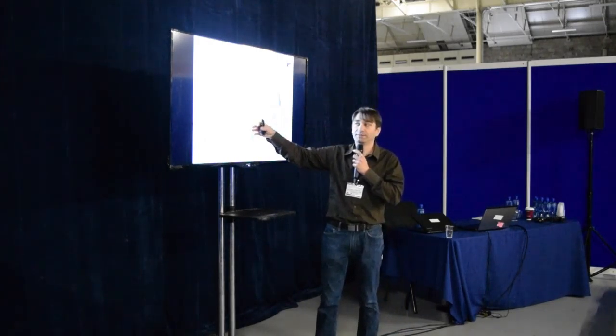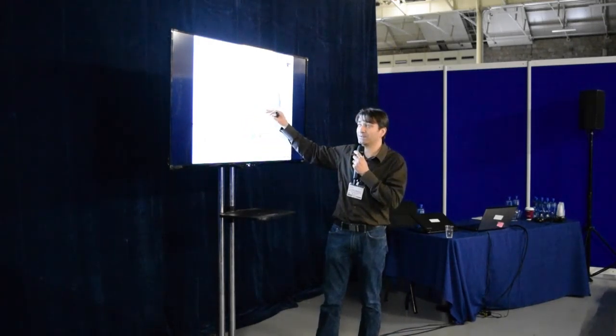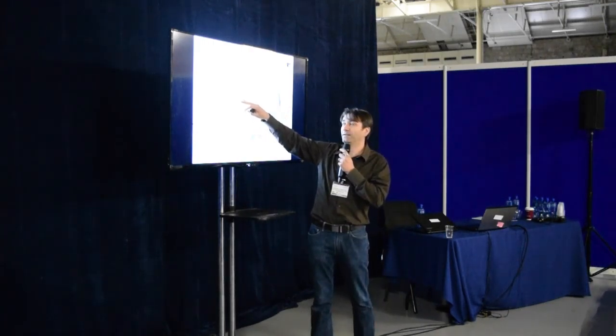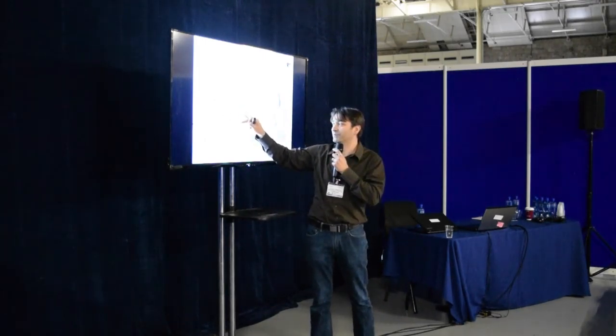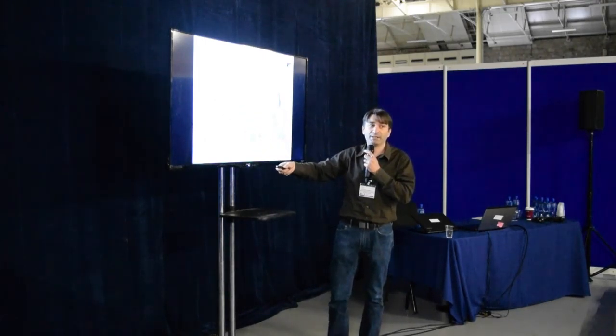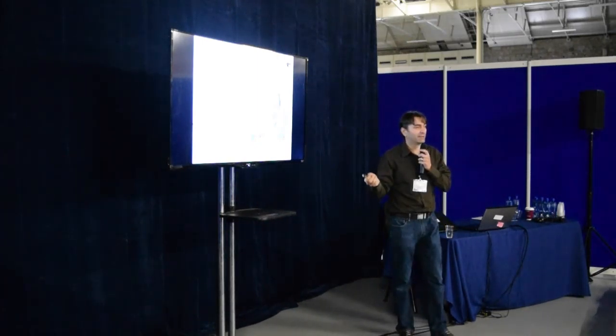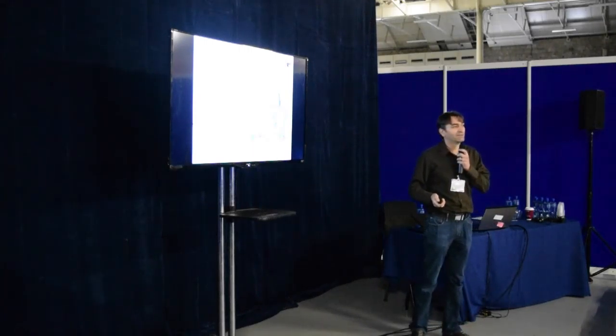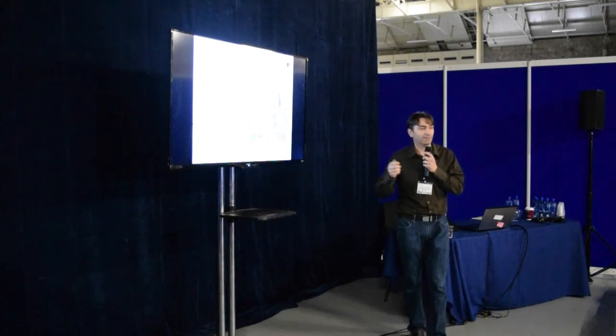Before cracking, bacteria is in a dormant state, just sleeps. And when a crack occurs in concrete, water penetrates into the crack, which reduces the acidity of the concrete. Then bacteria wakes up and starts eating and producing calcite. Calcite closes cracks, and once the crack is closed, acidity increases, and bacteria goes back to sleep. As long as there is food, this process can be repeated over and over again.